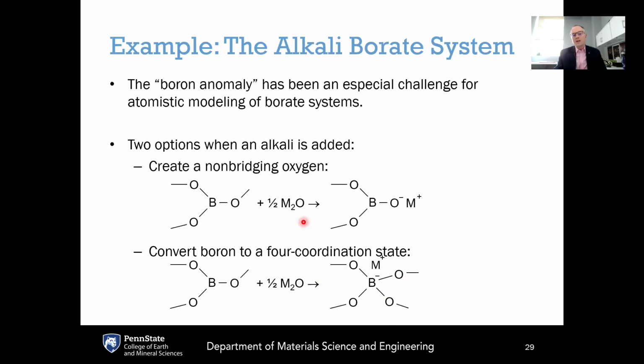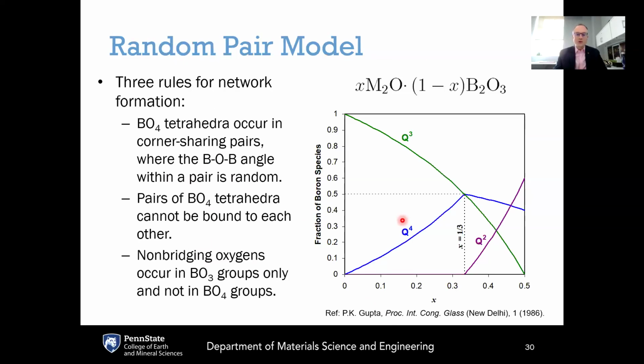The other option is that adding modifiers to the borate glass can actually break up bonds. It can form non-bridging oxygens, where now instead of having three bridging oxygens here on the left, it creates one non-bridging oxygen so that there's only two bonds here to other units. This actually decreases the connectivity of the network. And so what makes the boron anomaly so interesting is that modifiers could either increase the connectivity of the network or decrease the connectivity of the network, depending upon their specific structural role.